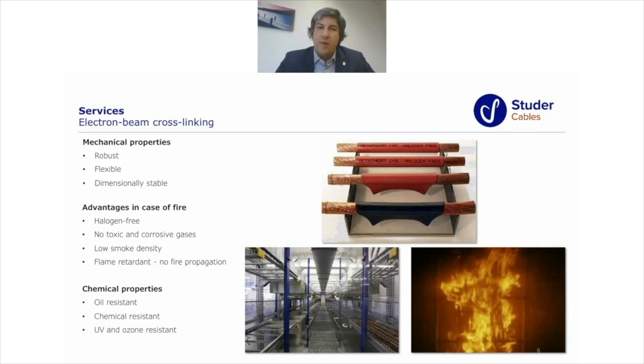On the other hand, if you apply the electron beam cross-linking, you are affecting the polymeric structure for a specified time in a specified strength and performance. And once the process is done, it's finished. And the elasticity or the physical properties of the cable will remain unchanged for the whole lifetime of the installation. So you see a significant difference, and electron beam cross-linking makes a huge difference.